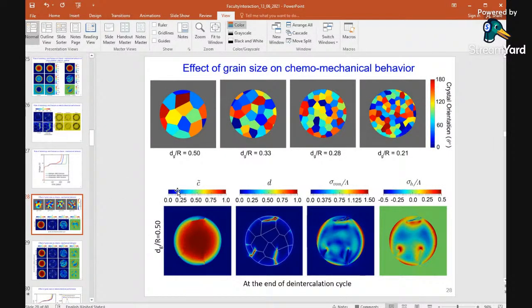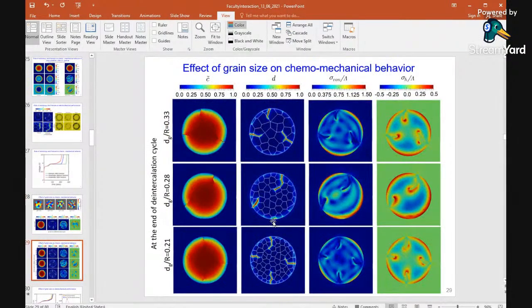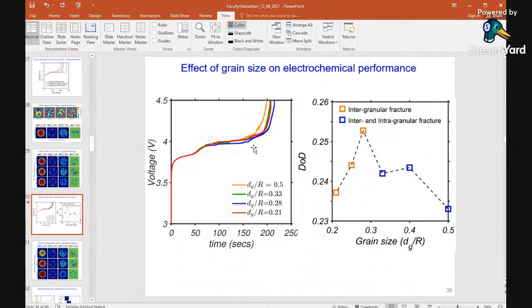Next we have studied different grain sizes, and we try to understand how the crack is developed in each of these separate cases, and what type of fracture is being developed. We see a detailed correlation, and we can really understand how the crack is being developed. When we have a finer structure, we can see that multiple cracks are generated, and all the cracks are coming from the interfaces, and a very complex stress field is generated. Now if we collect all the information together, we can see the voltage versus time for different grain sizes.